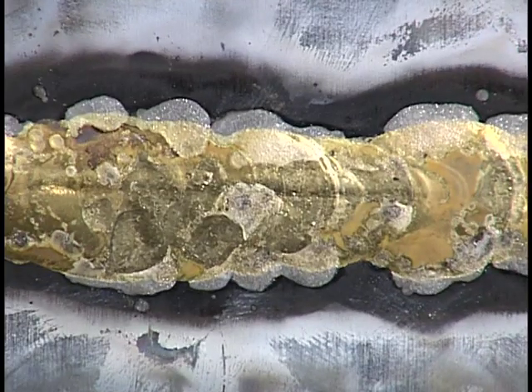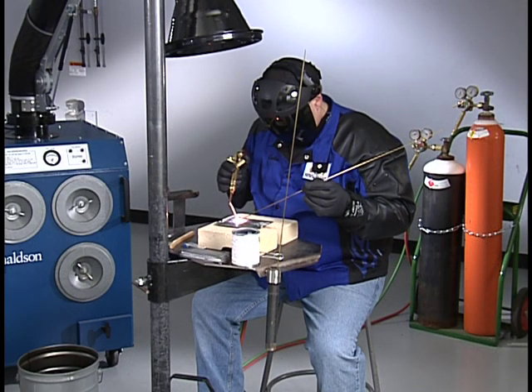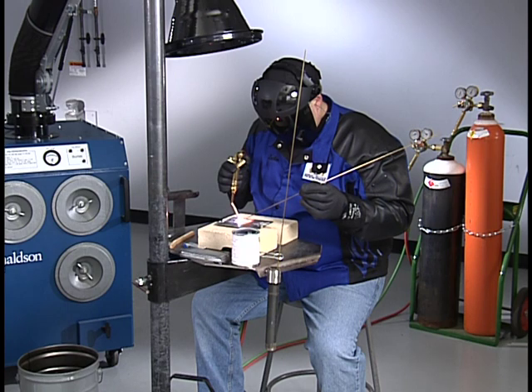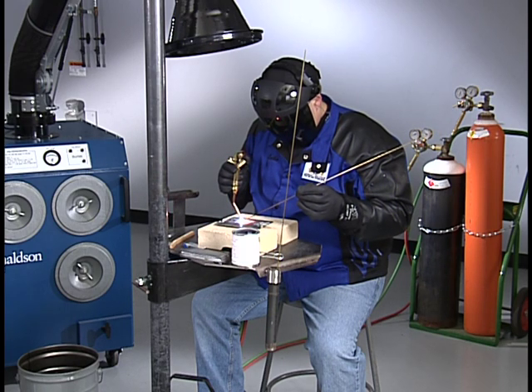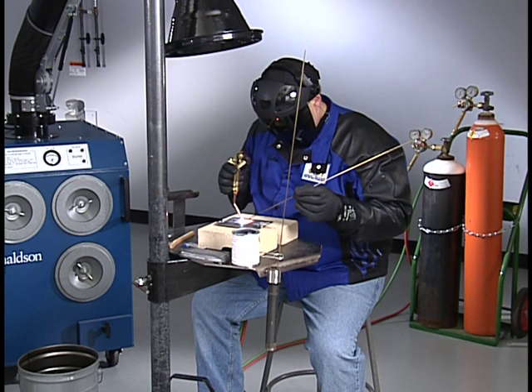The visible white powder indicates the presence of oxidized zinc. This is an indication of too much heat on the braze weld joint. The fumes from burned zinc oxide and from flux should not be inhaled, so remember, proper ventilation is always necessary with any brazing process. With care and practice, you should be able to produce quality braze welds.